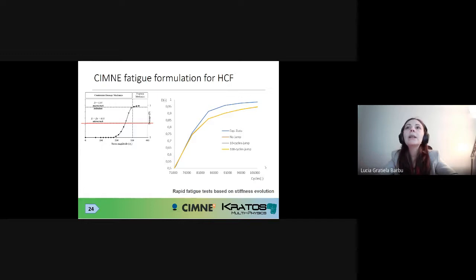And what we've seen is that we've gotten quite a good agreement between the numerical and the experimental part. I have to say that we only analyzed the damage or the change in stiffness after a specific level of damage, which is 0.5. Actually, here there's a typo, because this is what was able to be detected by them through the open eye, let's say, experimentally. And you can see here the adjustment between the numerical and the experimental curve.